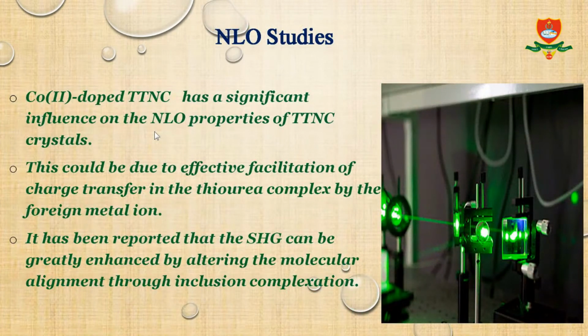NLO studies. Cobalt-2 doping has a significant influence on the NLO properties of TTNC crystals. This could be due to effective facilitation of charge transfer in the thiourea complex by the foreign metal ion. It has been reported that SHG can be greatly enhanced by altering the molecular alignment through inclusion complexation.